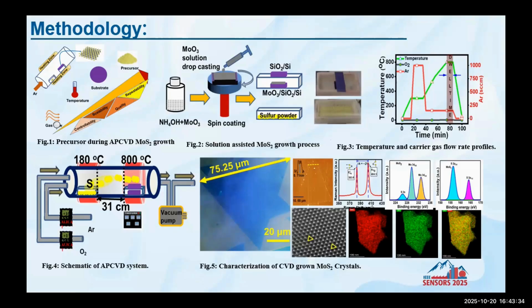So this is a camera image of how we kept the samples and the sulfur powder. These two alumina boats are loaded in the respective heating zones inside the quartz tube. Sulfur is loaded at 180 degrees centigrade, while the MoO3 substrate-loaded boat is kept at 800 degrees centigrade. The distance between these two alumina boats is optimized, and it is 31 centimeters. Argon and oxygen are used as carrier and assist gas respectively. This is the temperature profile, carrier gas flow rate profile, and assist gas flow rate profile during the growth of monolayer MoS2.